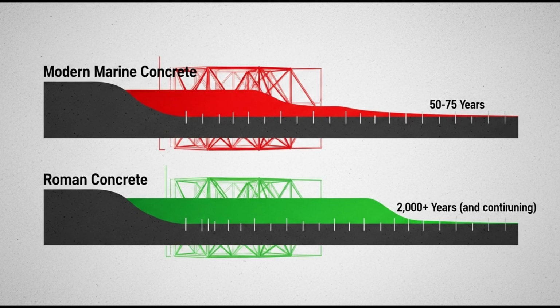Typical marine concrete lifespan, 50 to 75 years in harsh environments, even with protective measures. Roman concrete, 2,000 plus years and counting, still structurally sound, still functional. The protective mechanism. The tobermorite acts as a protective barrier. It's highly impermeable, blocks further seawater penetration. As it forms in cracks and voids, it seals the concrete, makes it denser, more resistant.